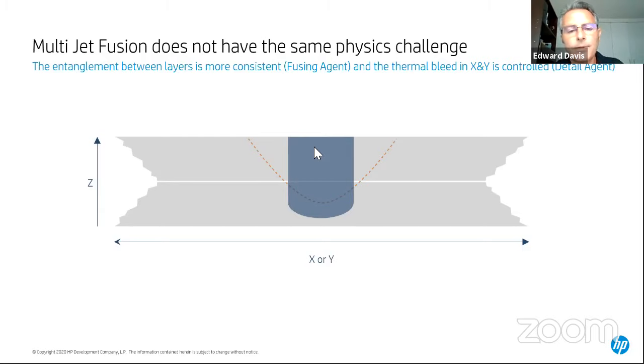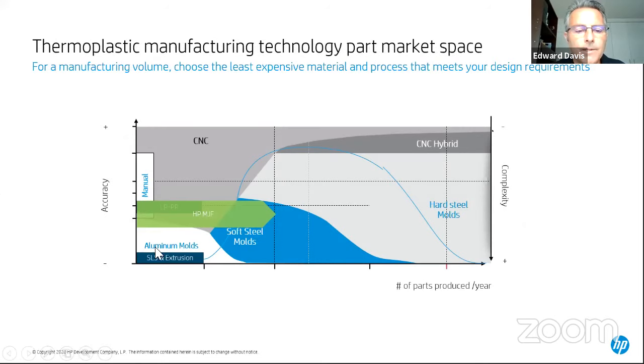So with that, we're actually able to get some very good dimensional tolerances. We've done our own internal studies. There's a different talk I can give, but in fact, for those of you who are familiar with the scale, we can attain an international tolerance grade 13 with a CPK of 1.33, which is similar to the tolerances you can get with soft steel molding. You can get much better tolerances with hard steel molding, but it's very similar to what you can get with soft steel molding.